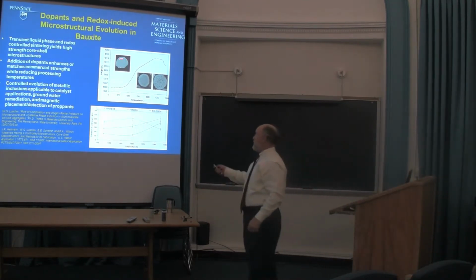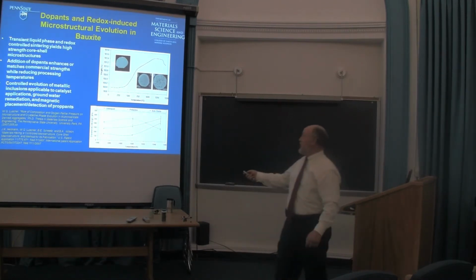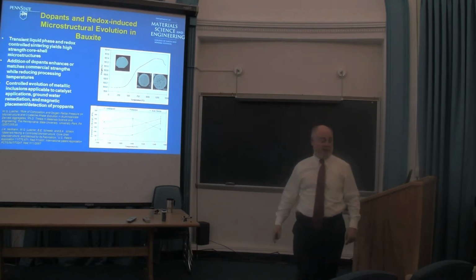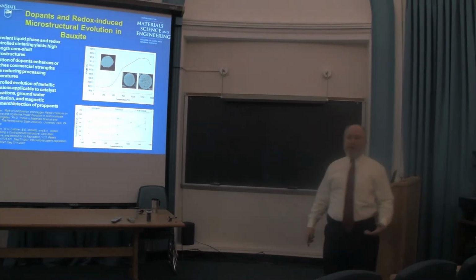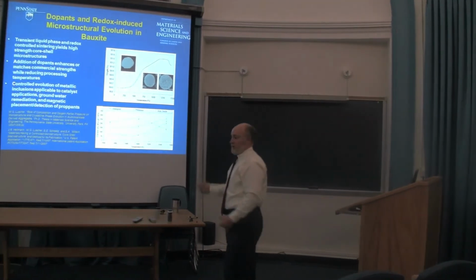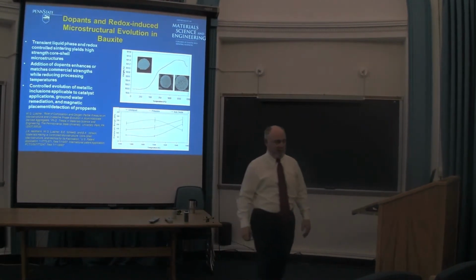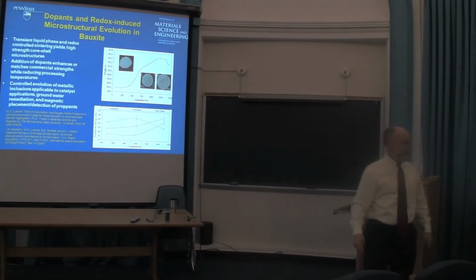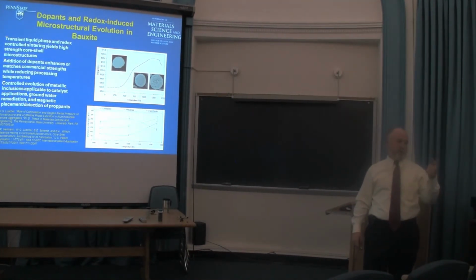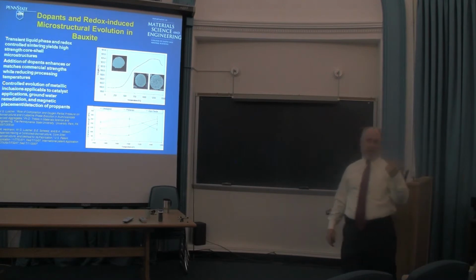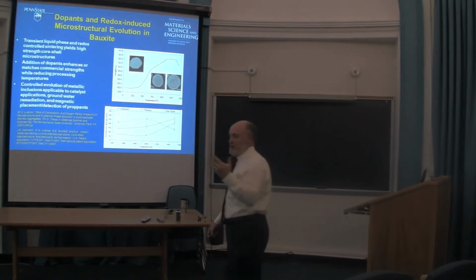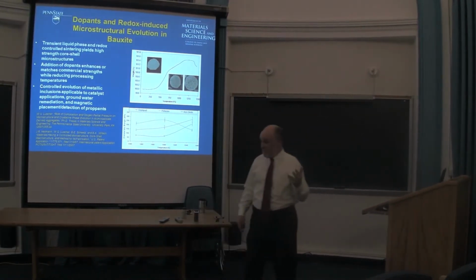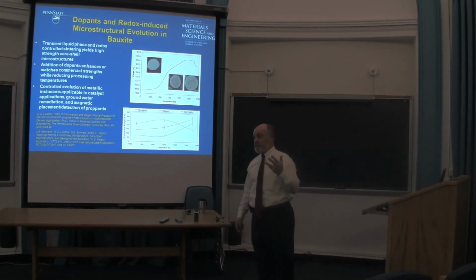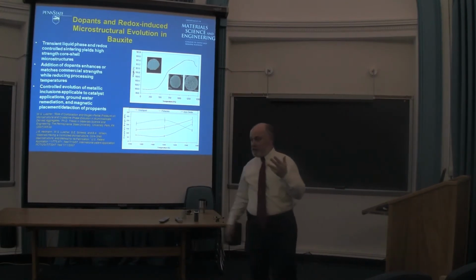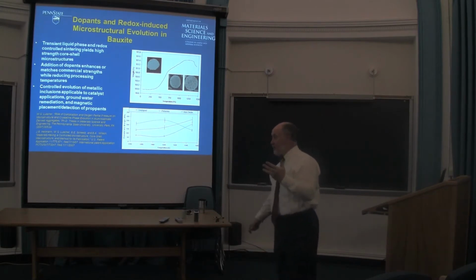Okay? The other thing about it is that dense particle after sintering was decorated both internally and on the surface with our zero-valent dopant. In this case, iron. It could be titanium, it could be some other transition metal. They're catalytic. So now we got a proppant particle that's dense with a catalytic surface. It might possibly be useful to us in situ treatment of hydrofracturing fluids, right, which also wound up getting patented, right, as part of the core shell patent.